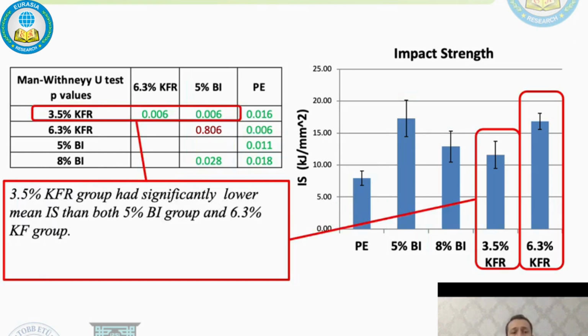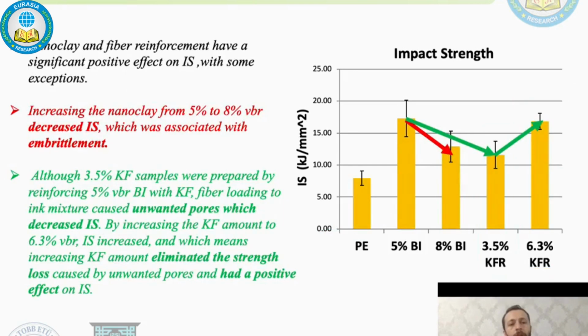The 3.5% Kevlar fiber group had significantly lower mean impact strength than both the 5% base ink group and the 6.3% Kevlar fiber group. When all results are examined, the following conclusions can be reached. First of all, nanoclay and fiber reinforcements have a significant positive effect on impact strength, but there are some exceptions. The first one is about nanoclay. Increasing the nanoclay from 5% to 8% decreased the impact strength, which was associated with embrittlement, because obviously increasing the nanoclay amount made specimens more brittle and it decreased our impact strength.